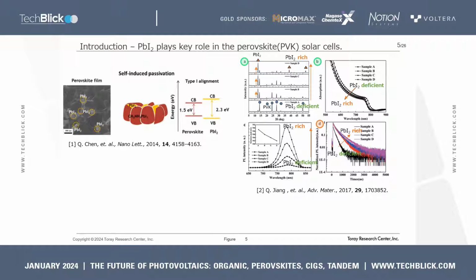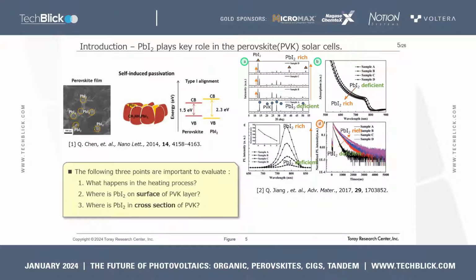UV-Vis absorption spectra results are shown in Figure B. It was also found that the PbI2 content in the perovskite layer obviously influences the absorption and also the band gap. Emission and external quantum efficiency, EQE, are shown in Figures B, C, and D. The blue shift of absorption could be due to the passivation of defects in FAPbI3 by PbI2. Time-resolved photoluminescence, TRPL, results showed that the lifetime of FAPbI3 was also significantly increased from 110 nanoseconds for PbI2-deficient sample A to 529 nanoseconds for PbI2-rich sample D, indicating that PbI2 actually passivates the perovskite defects significantly.